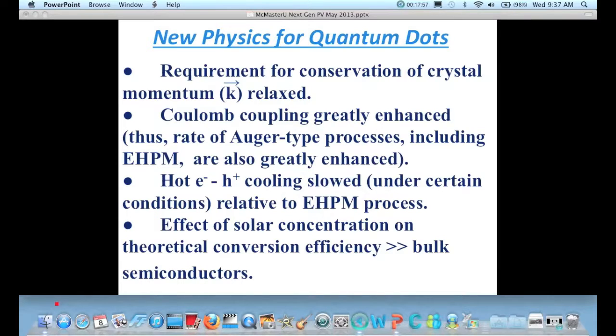Secondly, the competing process for those high-energy electrons and holes created by the absorption of a high-energy photon is the emission of phonons, which produces heat. And so that's where something like 50% of the energy coming in from the solar photons is lost because you convert the high-energy electrons and holes created by the high-energy photons of the solar spectrum into heat. And if you can avoid that by either using those photons to generate more electrons or to extract the hot electrons before they emit phonons and cool to the lattice temperature, you can increase the efficiency quite dramatically.